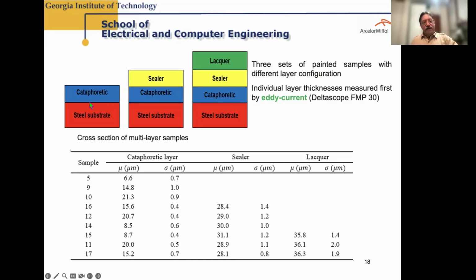The way this is done is the first layer is put down, then an eddy current measurement is made. Then the next layer is put down, then another eddy current measurement is made, and then the next layer is put down, followed by another eddy current measurement. Now, this is very time-consuming and laborious. It also does not reflect production, where this multi-layer coating might be put down before the previous layer is totally dry. Okay, so the laboratory measurement using an eddy current measurement is not even that realistic.